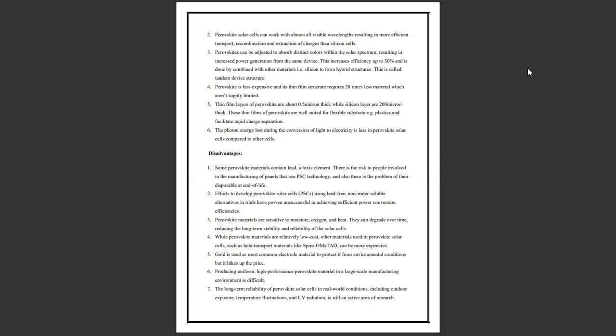Perovskite is also less expensive and its thin film structure requires 20 times less material, which is not supply limited. Thin film layers of perovskites are about 0.5 micron thick, while silicon layers are 200 micron thick. These thin films of perovskites are well suited for flexible substrates such as plastics and facilitate rapid charge separation. The photon energy which is lost during the conversion of light to electricity is less in perovskite solar cells as compared to other solar cells.